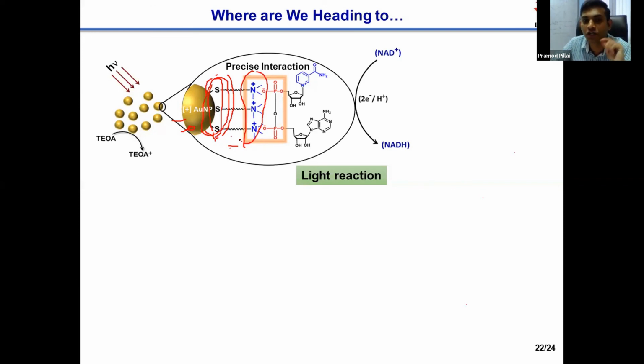So what we do is we control the solubility of two ligands in such a way that the more soluble ligand will be absorbed more on the surface of the nanoparticle. Like that, we control the ratio between plus and minus ligands on the surface. To make a homogeneously charged nanoparticle is very easy, I would say, but to make a heterogeneously charged nanoparticle, there is a challenge. So there you have to play with the solubility, the kinetics, the temperature, and all those parameters will affect the ligand exchange process.